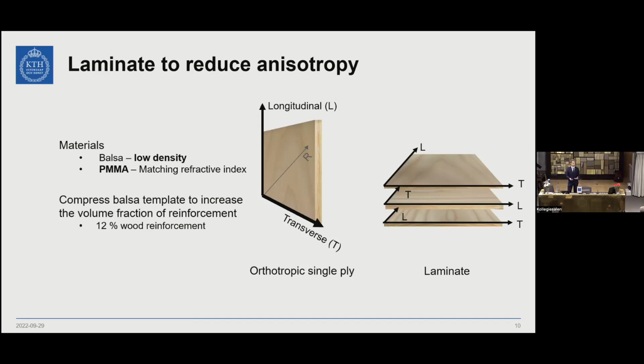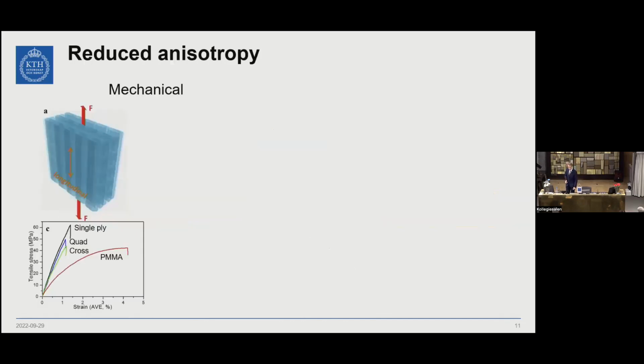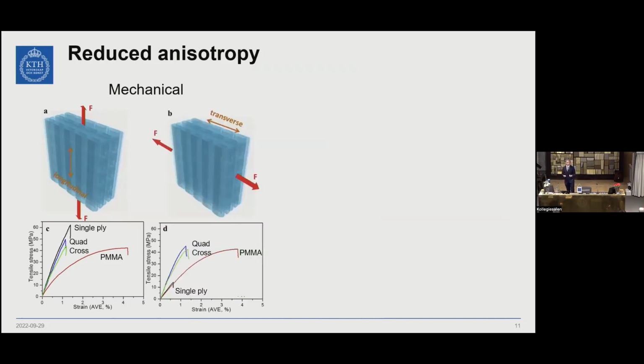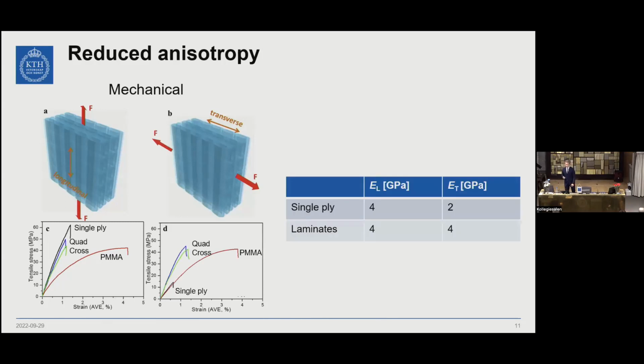In order to improve the mechanical properties, we compressed the wood veneer so we could have a higher volume fraction of the reinforcement. We did mechanical tests in, one can say, the longitudinal direction. And you can see that the single ply and the laminates are quite the same. The strength is a bit better for the single ply. When we do it in the transverse direction, you can see that the single ply is much worse than the laminates. But the laminates still have similar properties. So it becomes more isotropic in the plane. And here are the values. You can see that it's quite the same for the laminate in both directions.